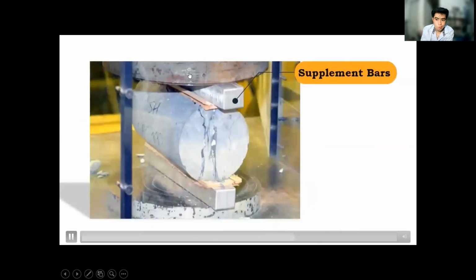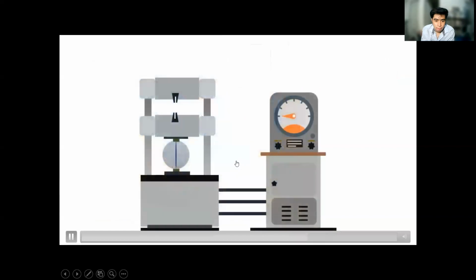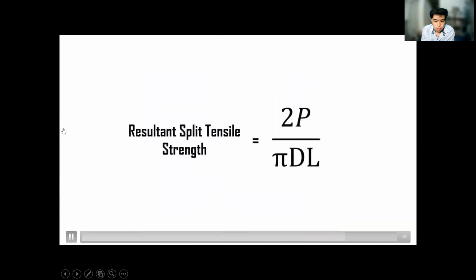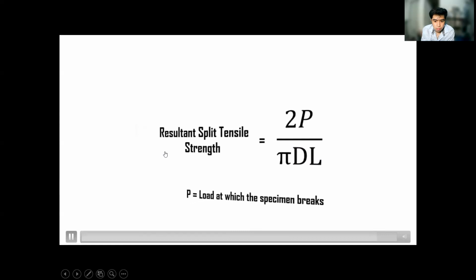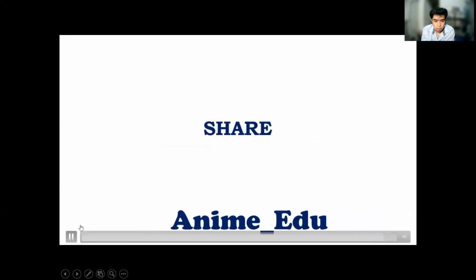Sometimes, supplement bars are placed on top of the plywood depending upon the diameter of the specimen. Now, apply the load continuously at a rate within the range of 1.2 to 2.4 MPa per minute. Finally, note down the load at which the cylinder fails by developing cracks. The resultant split tensile strength is calculated by the equation 2P divided by pi times D times L, where P is equal to the load at which the specimen breaks. Thank you for watching. Stay tuned. The best is yet to come. Kindly do like, share,